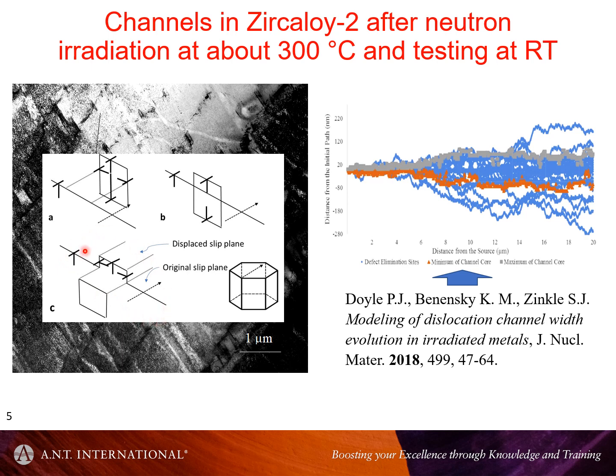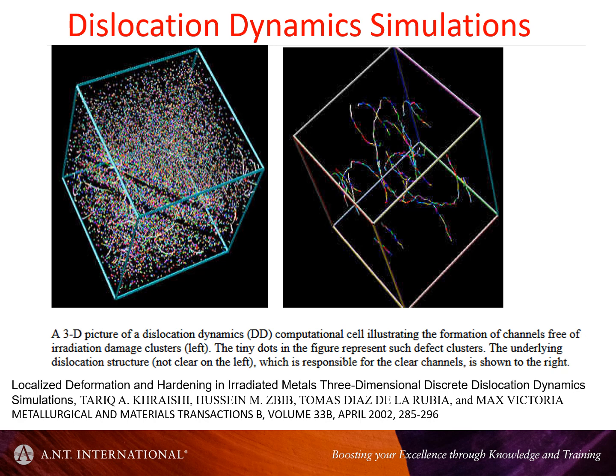The mechanism, which seems to be widely accepted, is simply incorporation of the dislocation loop into the gliding dislocation. And what we end up with then is this broadening of the plane over which the dislocation interacts with the material. Here's an example from some dislocation dynamics simulations. Unfortunately, I don't have the simulation. I asked Tariq if he had a video, and he said he doesn't, so he gave me a reprint. It basically shows in a simulation exactly what we showed there, that channel broadening, if you like, where dislocations travel through the material and sweep up the loops.